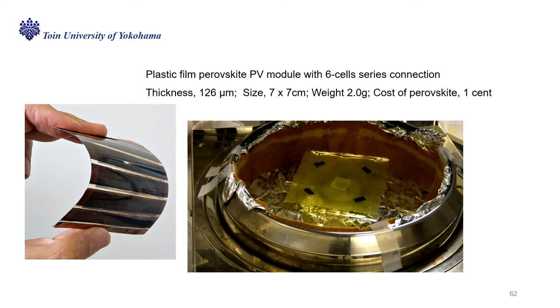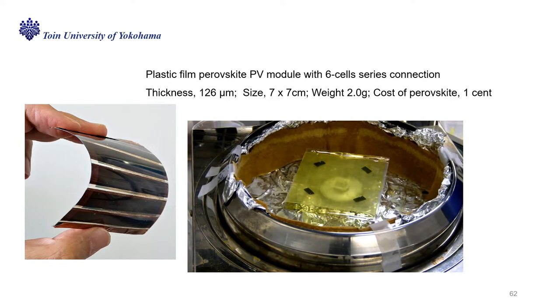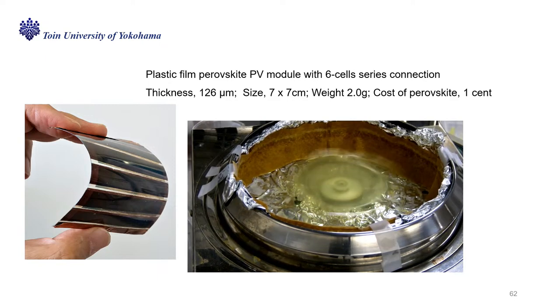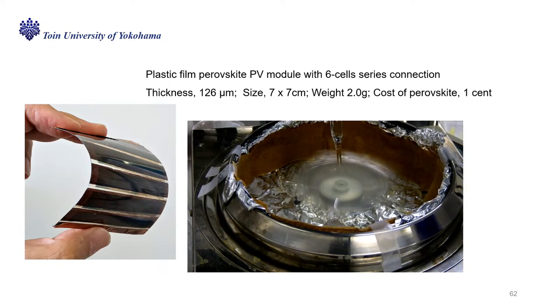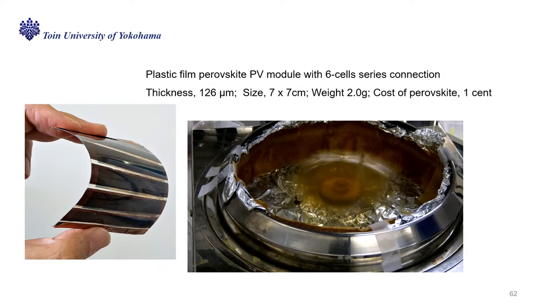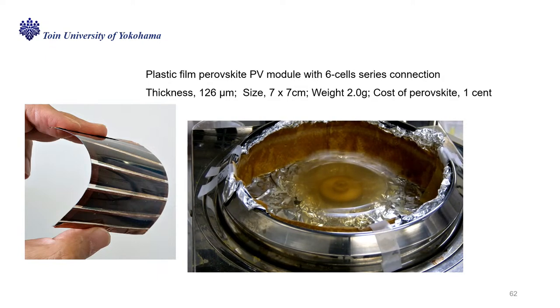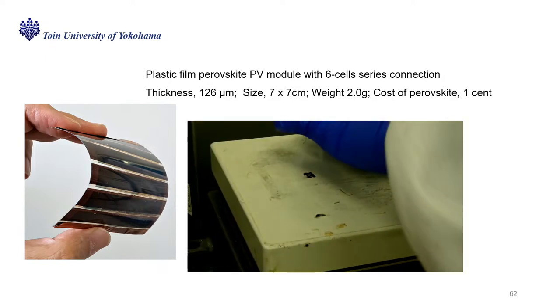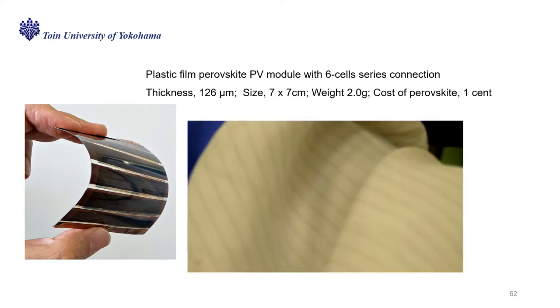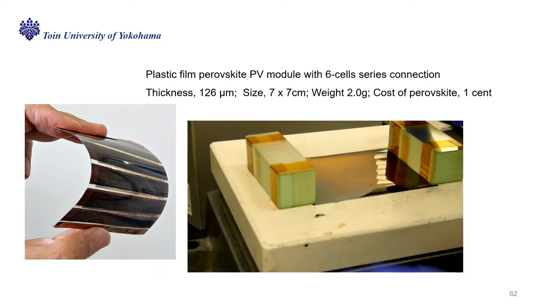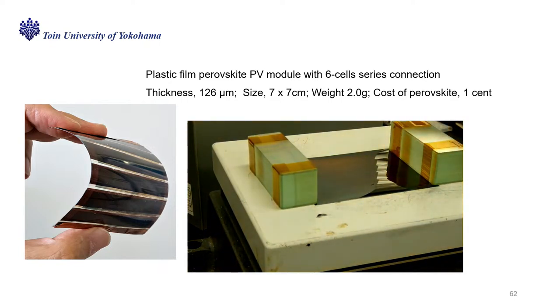So this is a video. We started with fixing plastic film on the glass stage, and this is a spin coating machine. To accelerate the crystallization, we dripped the anti-solvent, so-called chlorobenzene. So you can see a darkening color here. This indicates the production of perovskite solar cell. This is not perfect. Then we remove the plastic film to move to the hot plate to further heat the film up to 100 degrees Celsius. Then we can see the quick change of color to black, just in 2-3 seconds. Yes. So finished.